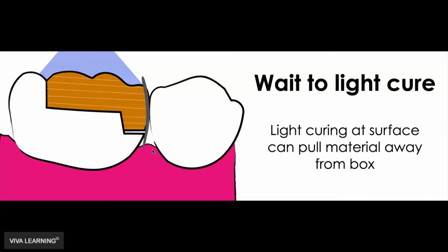So one of the little tricks with the dual cure bulk fill materials is that you want to let some of the chemical cure mechanism occur before you hit it with the light, because that does two things. One, it allows the material to cure towards the floor of the preparation, because that's where polymerization starts. If you hit it with a light, it could cure in that direction. But if you let it chemically cure first, then it can cure down towards the floor of the preparation. And also, just in general, letting it chemical cure versus light curing.